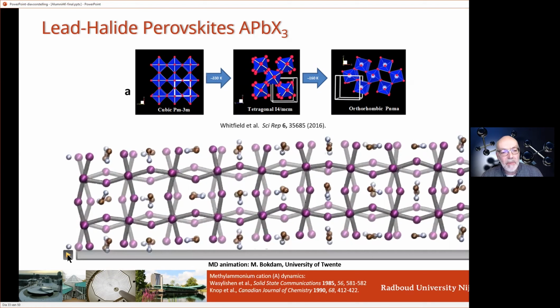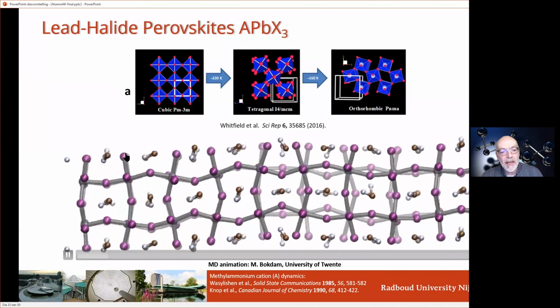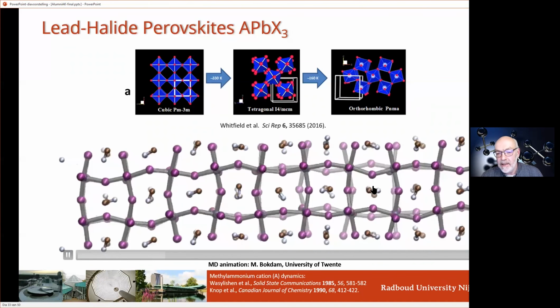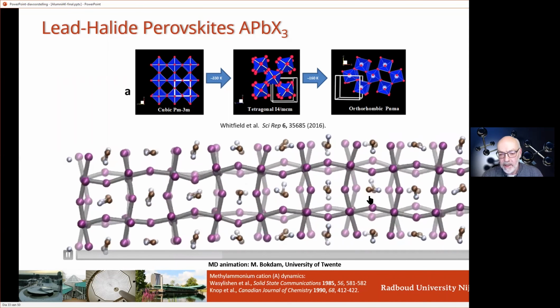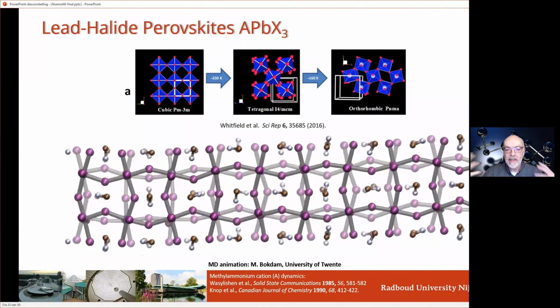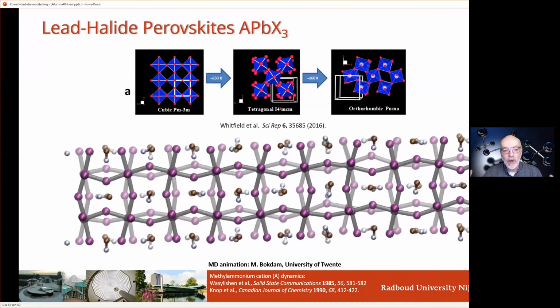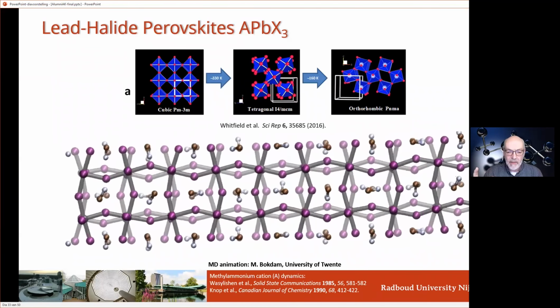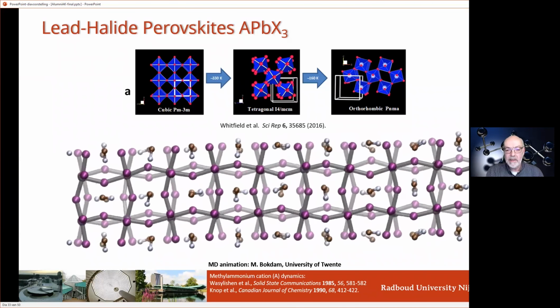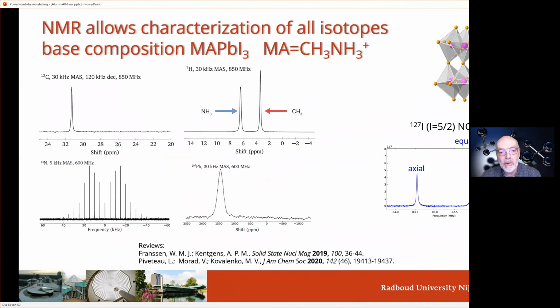But there is an interplay between this inorganic, say, lattice, and the cations. As I said, it's methylammonium, so it's an organic molecule. And there is this nice interplay and dynamics going on. And this is exactly where the strength of NMR is. We can look at the resonances. We can study all of the different isotopes. We can do carbon NMR. We can do proton NMR. We can study nitrogen, nitrogen-14. We can study lead. We can even look at the iodine. And then you don't even need a magnet because this so-called quadrupolar interaction is so big that you don't even need a magnet.